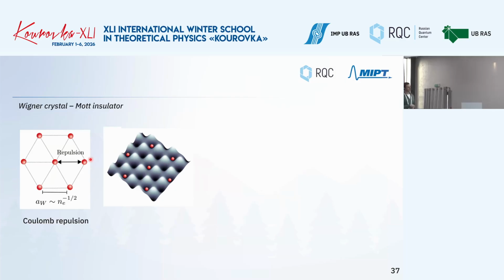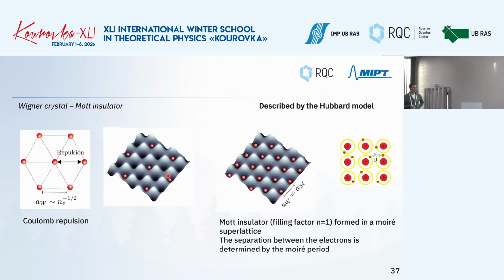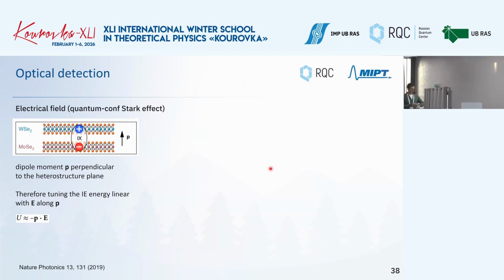As I mentioned, these electrons in the potential will crystallize, and there is a Coulomb repulsion between them, and they try to form the crystal. And then you can make either the Wigner crystal or the Mott insulator state. All of them are described by the Hubbard model, and in the Mott insulator case, you have a filling factor around 1, which is formed in the moiré superlattice. And this separation between the electrons is determined by the moiré period. So when you construct your material with a defined angle, you achieve the specific moiré period, and then you control this separation between the electrons.